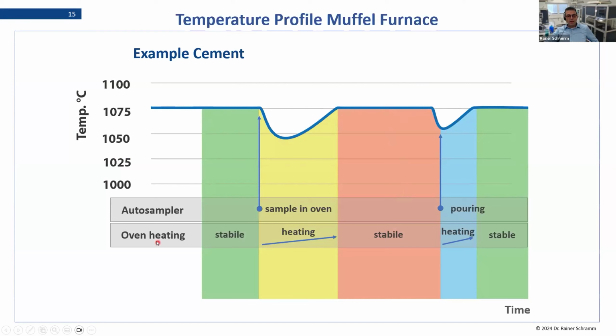So that means from the heating side, you have a stable heating situation, then you have to heat again, stable, heat again, and it's again stable. For the reproducibility of fusion, this is critical because in the moment you destabilize the furnace, you have to make sure that your heating is always working exactly in the same way. Only if this is the case, and you fuse the same sample twice in a furnace, will you get the same result. If the heating of the furnace was not really designed for that, then you will have a big error in the volatile elements.